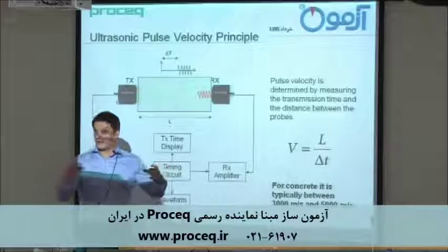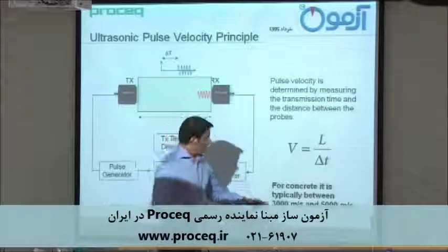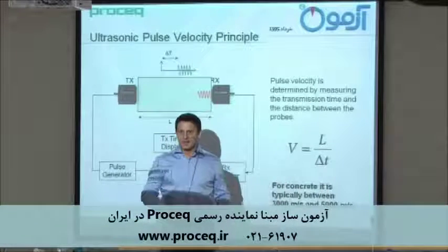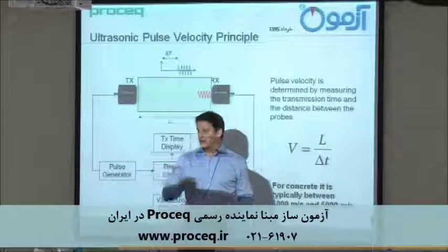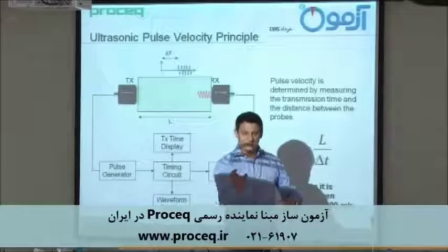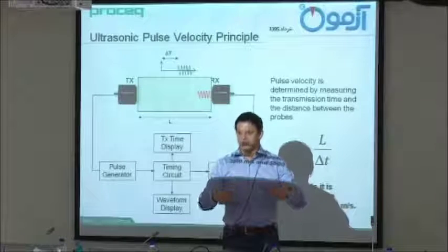So if you have a lot of rebars in, you get a high speed. Okay, remind yourself, steel has a higher velocity. Then you can say, okay, I check it somewhere else on another point. If it is all the time the same, still the calibration is done on the concrete on site, then the steel is included.